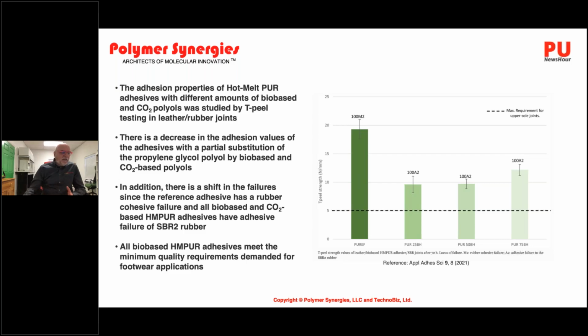So if you want sustainability, you have sustainability here because of these bio-based polyols that are being used, and they exceed the strength performance that's necessary. But also, if you can change the mode of failure, your overall performance may be greater. These are the types of things that you have to think about when you're designing an adhesive system. What these bio-based polyols allow us to do is not only get greater thermal stability, but form different types of network polyurethane structures, which can have an advantage in certain properties over others. And keep in mind, in polyurethane chemistry and polymer chemistry in general, there's no perfect polymer and there's no perfect polyurethane. It's all a balancing act of performance and properties and cost and the things that you're trying to achieve in your adhesive or in your polyurethane. It's a balancing act that's based on the structures of the molecules that you're reacting.